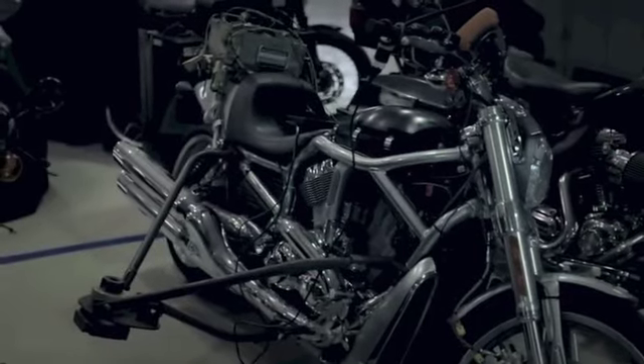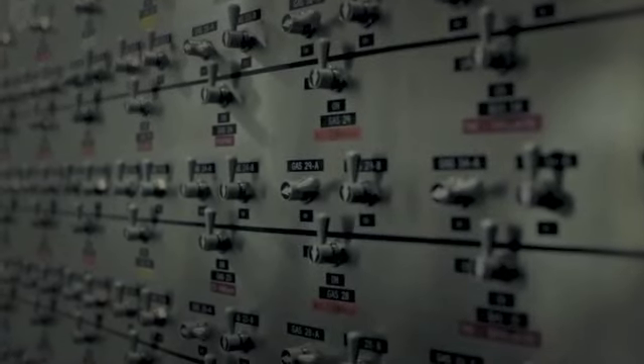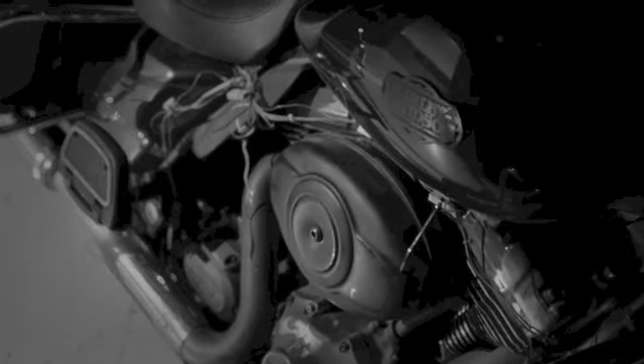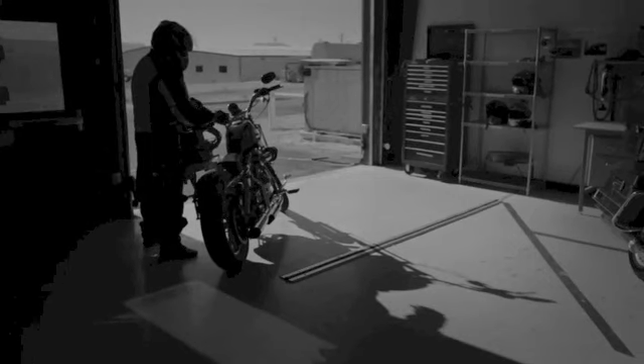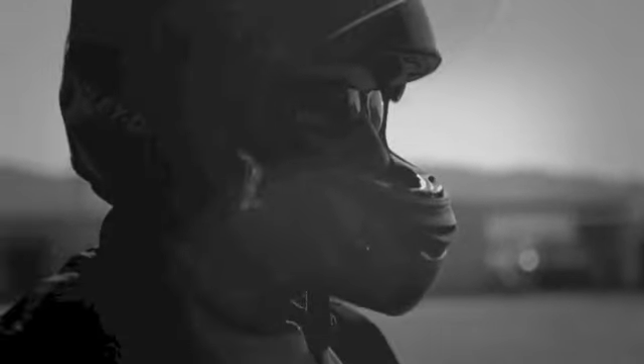In the testing of Harley-Davidson products at the Arizona Proving Ground, we try to simulate a lot of worldwide climates by doing corrosion testing, where we put the vehicles inside a humidity chamber at high temperature and high humidity, in conjunction with salt spray and operating over some rough environments, just to help simulate more worldwide conditions that would be experienced in climates where there's a lot of rain or corrosive environments like a salt or a coastal city.